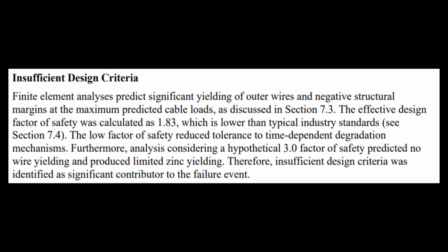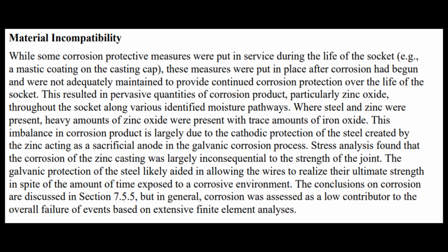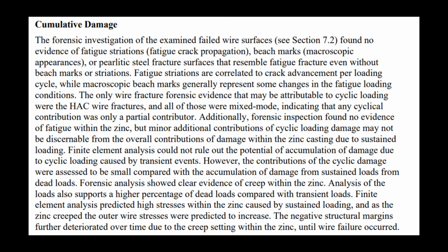Additionally, the sustained dead load versus total load is significantly higher than for typical open socket terminations in bridges, hoists, etc. The NASA report also states that as the casting cooled and solidified, shrinkage occurred between the casting cap and the socket cone inner diameter, leaving a gap along the insides of the zinc casting nearest the casting cap. Additionally, 8 wire ends were found to touch the socket cone inner diameter, which provided a pathway for moisture intrusion. Additionally, this report notes that design verification lacked specific testing of creep, cyclic loading, and worst-case workmanship conditions. Credible failure modes were unqualified in the Arecibo Observatory application.